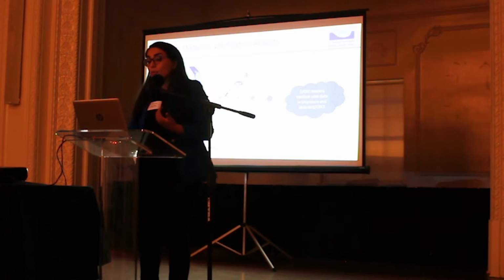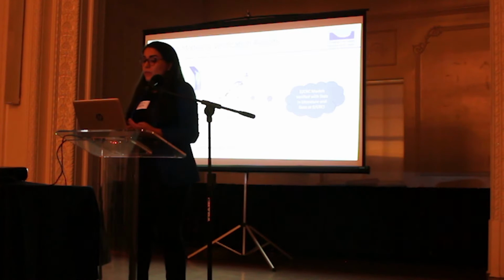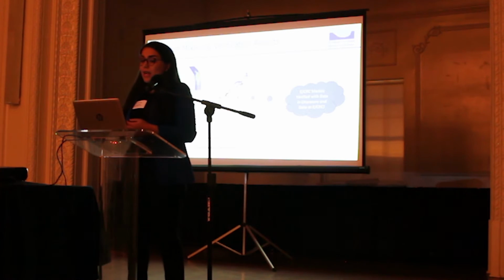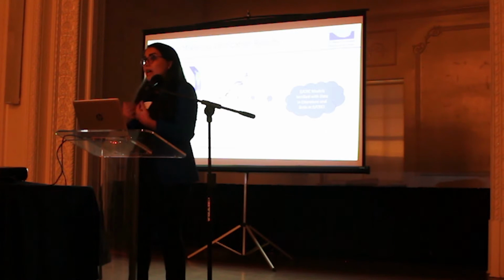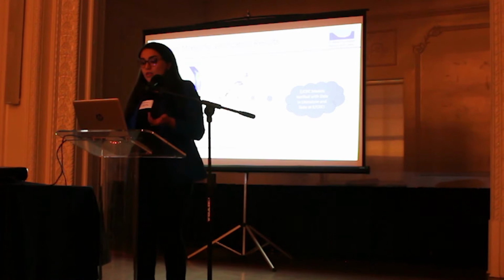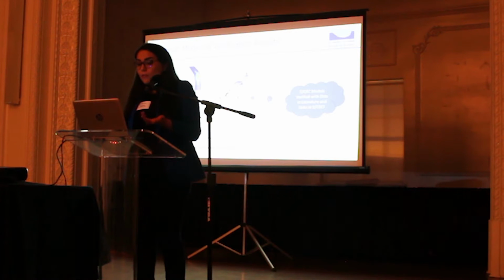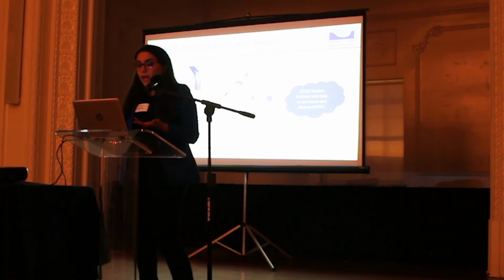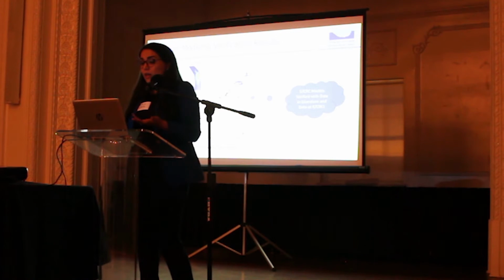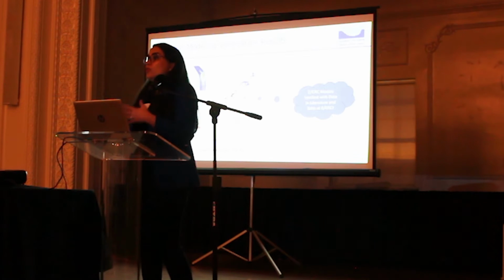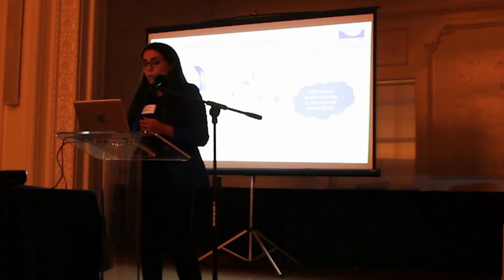So what we do is that we develop these models and we verify them with the data that we have in the literature, with the data that we gather at ECRC. So for example, this is one of our softwares where we have one-dimensional prediction against the experimental data. This black line shows the perfect agreement, and you see we have multiple experimental data from different researchers in the literature. And we are getting relatively good predictions compared to what API or previous practice was doing.